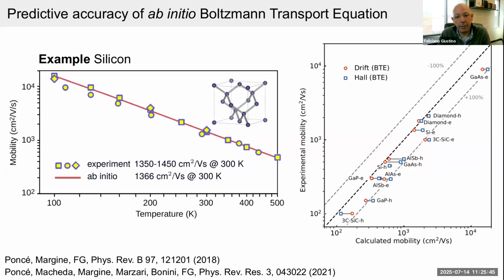Now, silicon is a little bit the best case scenario. If you look at other materials, the agreement is not as perfect. We tend to slightly overestimate the mobilities that are seen in experiments, but we're really talking about overestimation of the order of maybe 30%. And the mobility values really sweep many, many orders of magnitude. So a 30% agreement, we think, is good enough for, let's say, materials design.